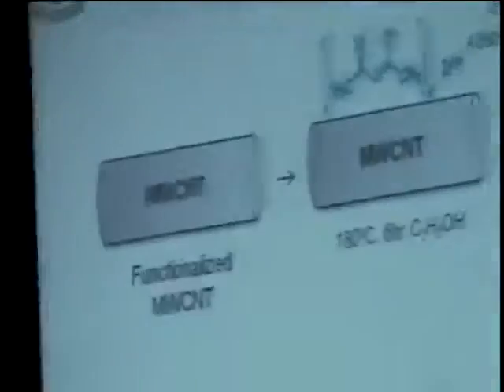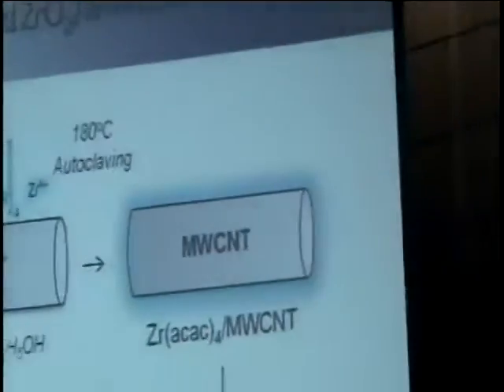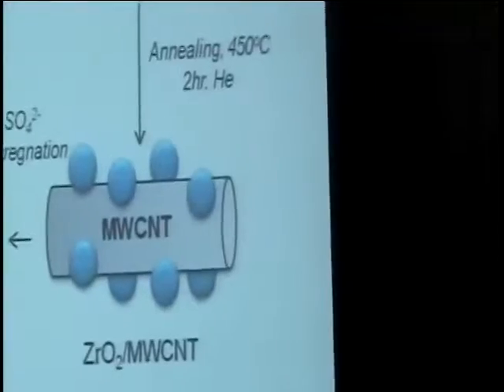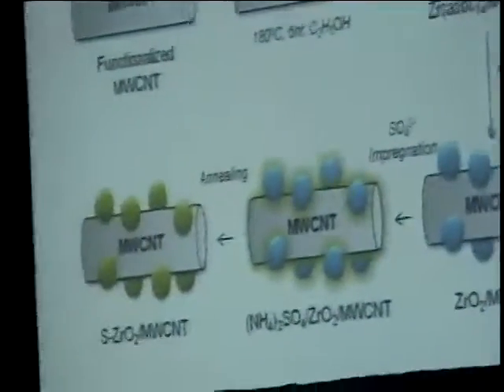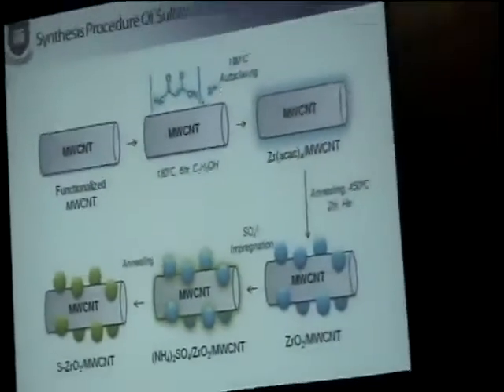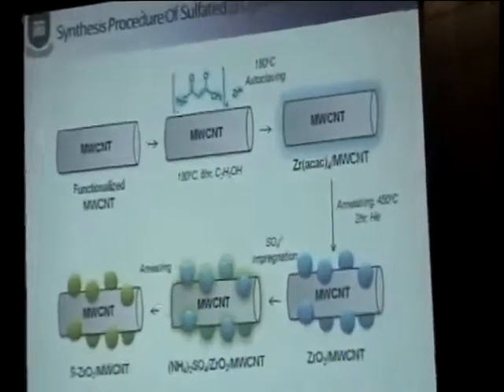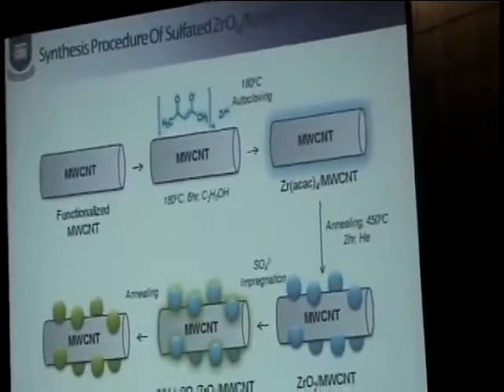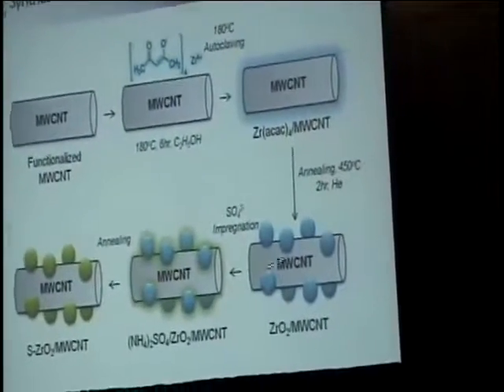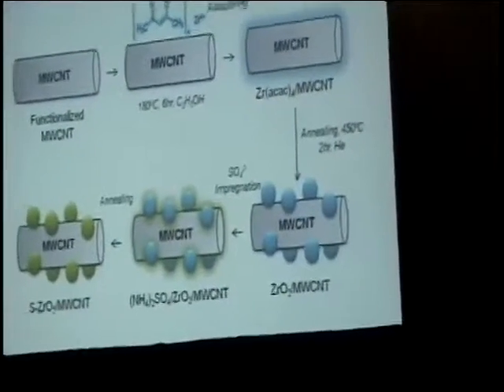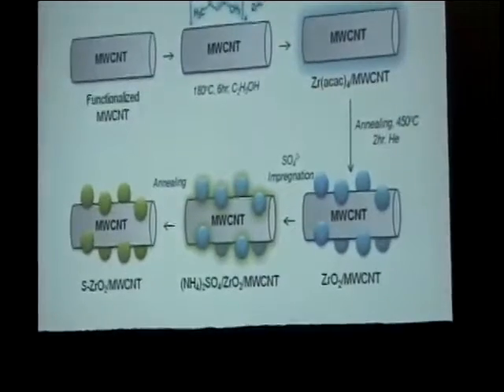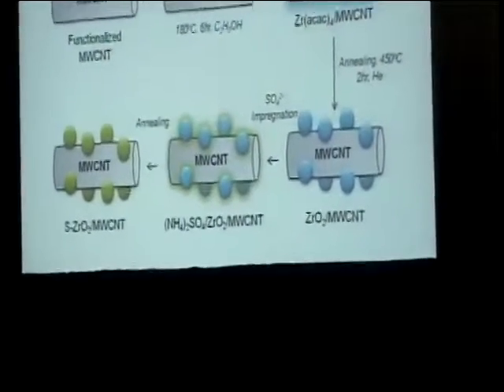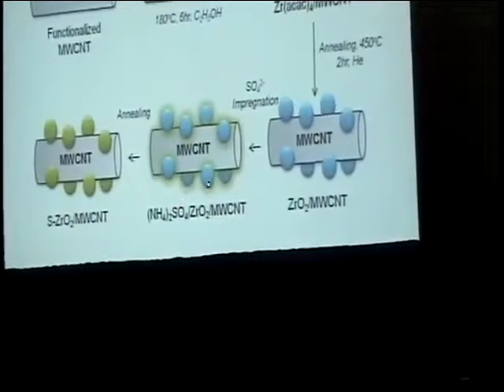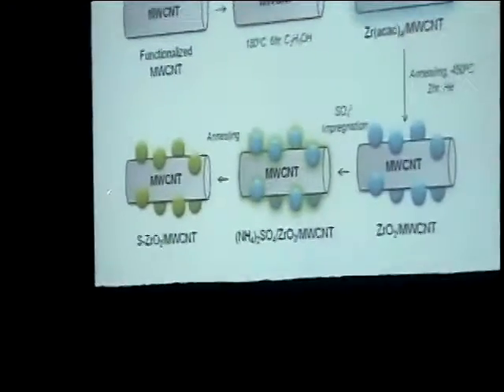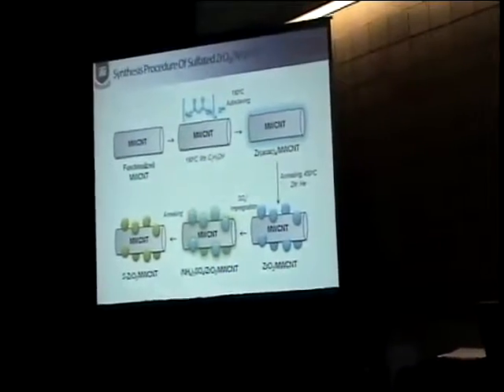So this is a cartoon of how we make these materials. The support is multi-walled carbon nanotubes, which are functionalized by oxidative nitric acid. We then graft a zirconium precursor onto those functional groups, and then that is annealed at 450 for 2 hours to crystallize the zirconium oxide. We can put in a little oxygen, but we can't use the traditional calcination because we burn up the tubes. And then we impregnate with ammonium sulfate and repeat this annealing at 450, and that's the catalyst that I'm going to be talking about. But I won't say any more about the preparation itself.